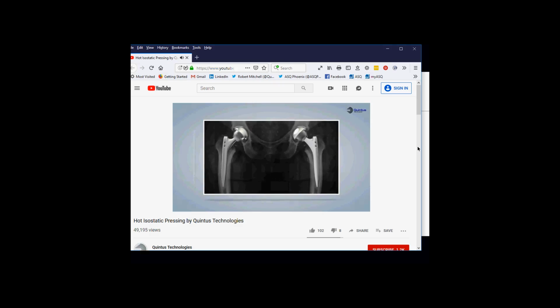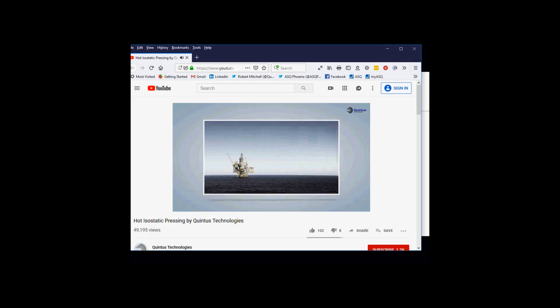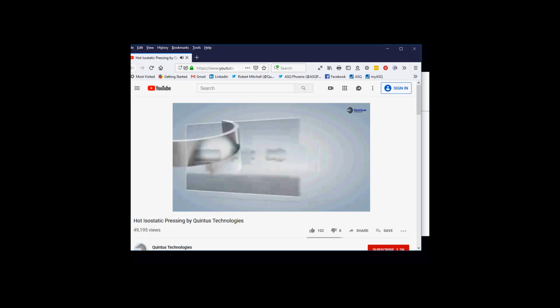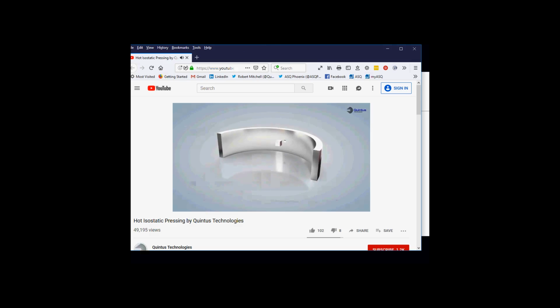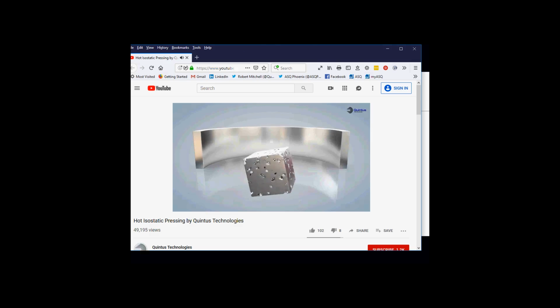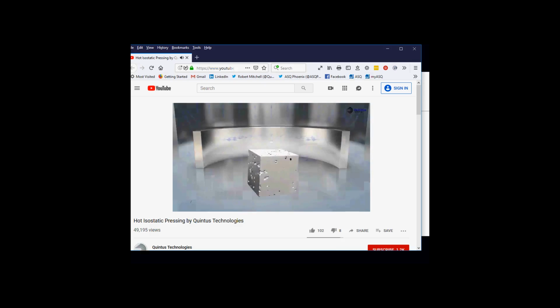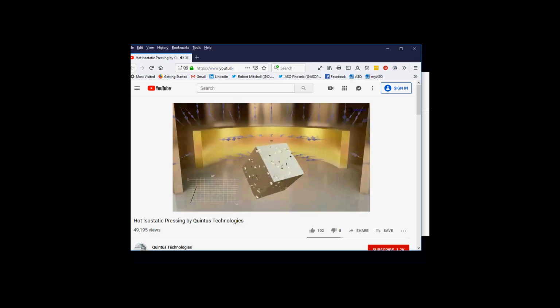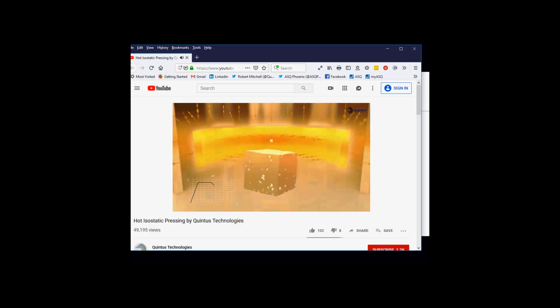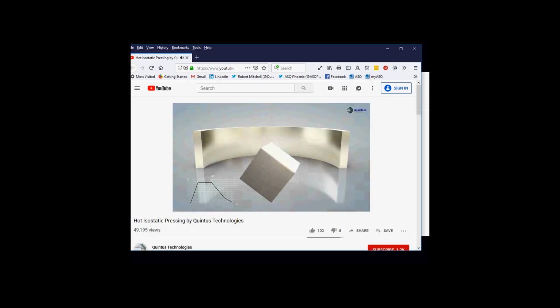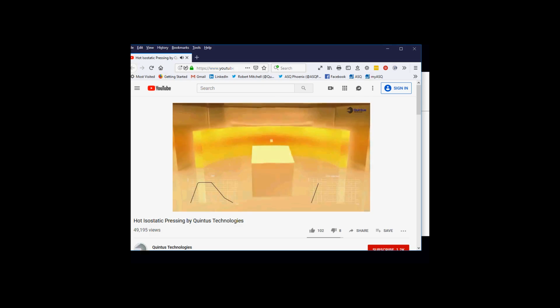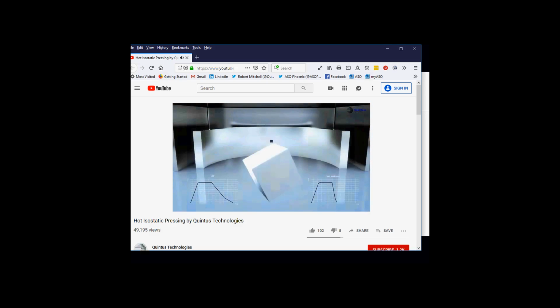We must minimize the risk of inconsistencies with our materials in order to be able to take product quality for granted. Materials formed from casting or additive methods such as 3D printing contain porosity or microcavities. These porosities must be reduced to eliminate the risk of premature breakage. This is usually done in two steps. Firstly, heat is applied under pressure in a HIP process, which reduces porosities and cavities. Secondly, the material is heat treated in a process where rapid cooling improves the fatigue and ductile properties. It would be an advantage if these processes could be combined to save energy and increase productivity.